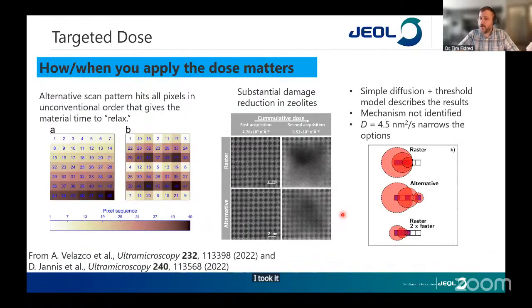So we're actually going to look at an asbestos sample. I took it out, so we're going to look at zeolites. The exact same amount of dose between two acquisitions. Under the classic scanning, you burn through the entire sample. Under the alternative, you can still make out the lattice. You can also drop the beam and have even less damage. This is just looking at apples to apples for the amount of dose.